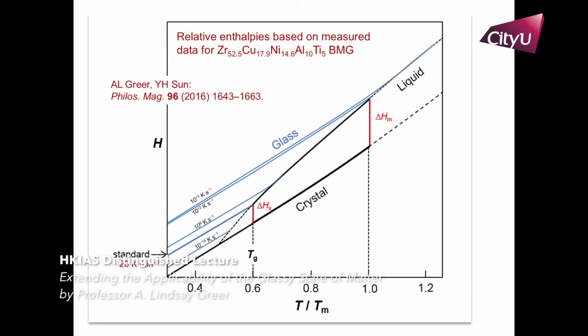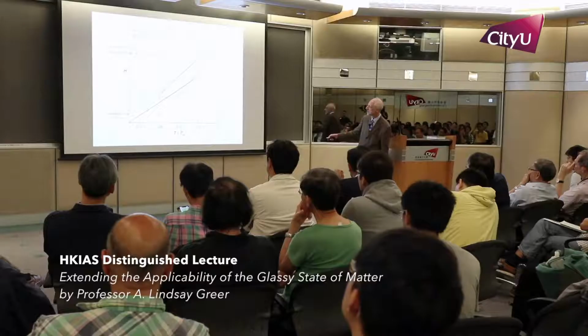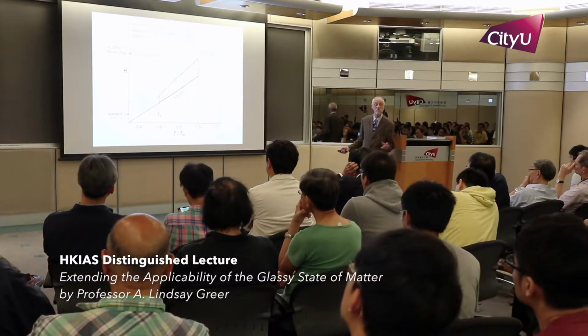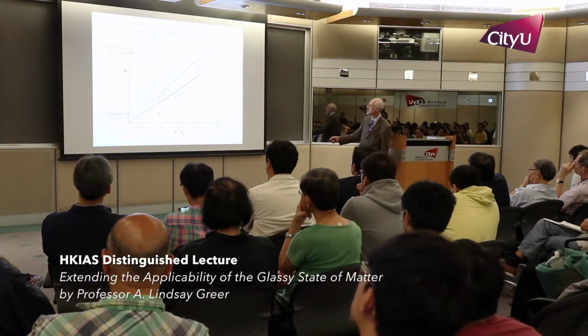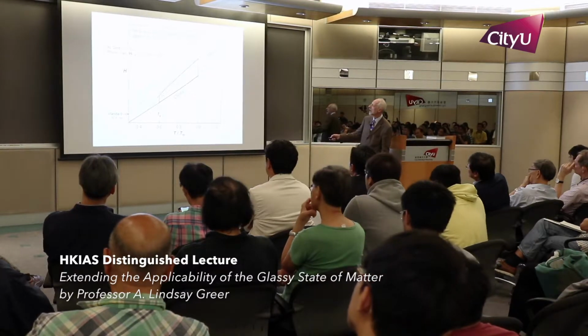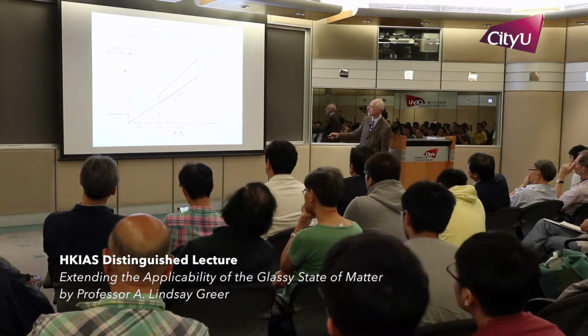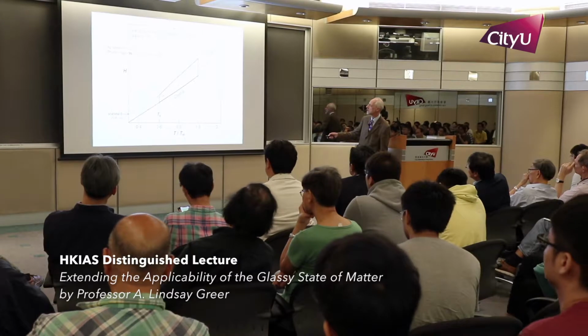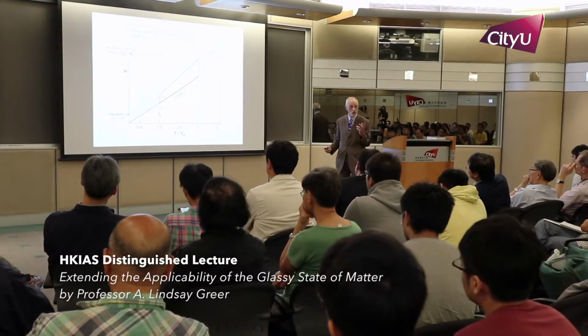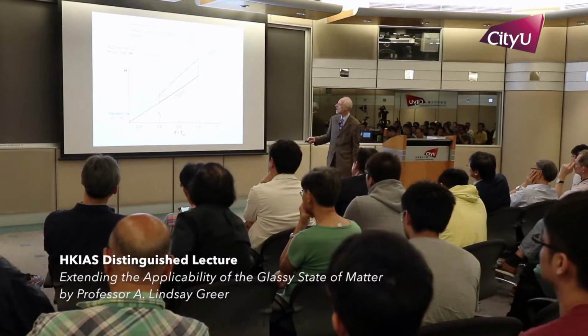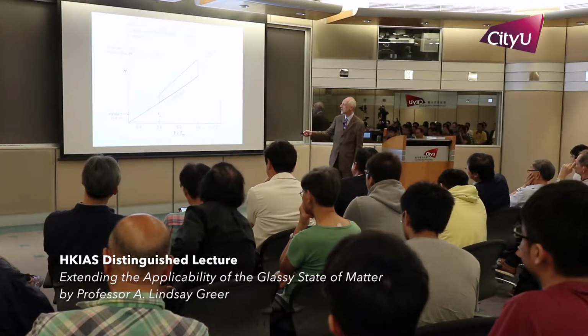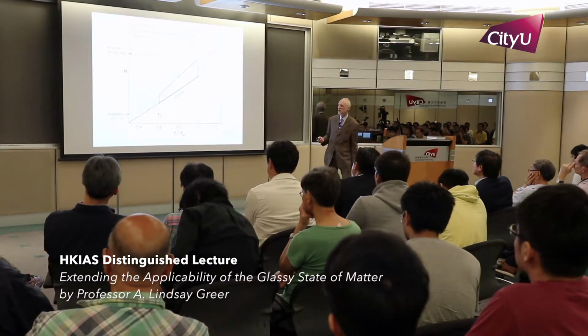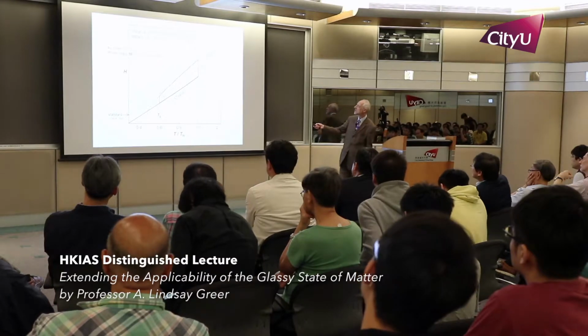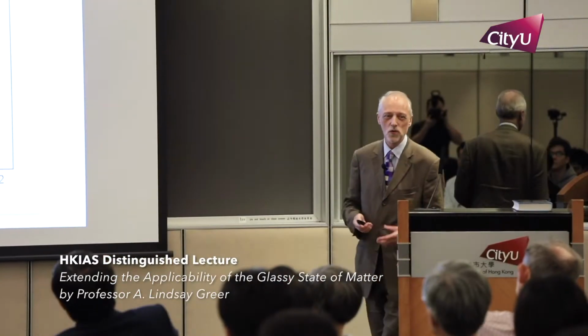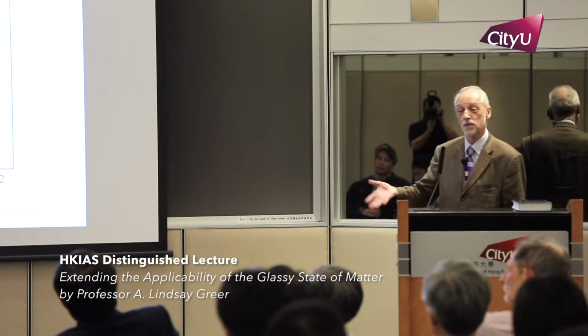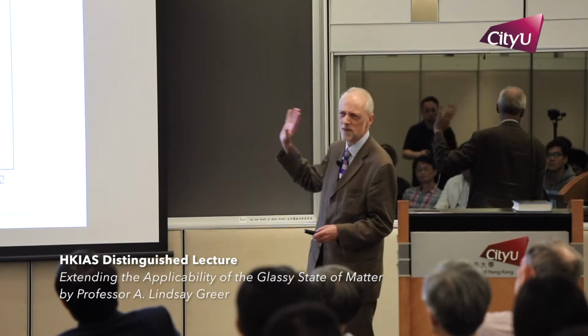If you'd had that ultra-stable glass, you would be down here, and the equivalent cooling rate is 10 to the minus 14 Kelvin per second. The highest rates go up to about 10 to the plus 13 or plus 14 Kelvin per second. We'll see how those can be reached later on. So the total energy difference is this range. That's quite a remarkable range in one phase because it's the heat of melting. So you can store that enormous difference in energies in one phase, something you could never do in the crystal state.